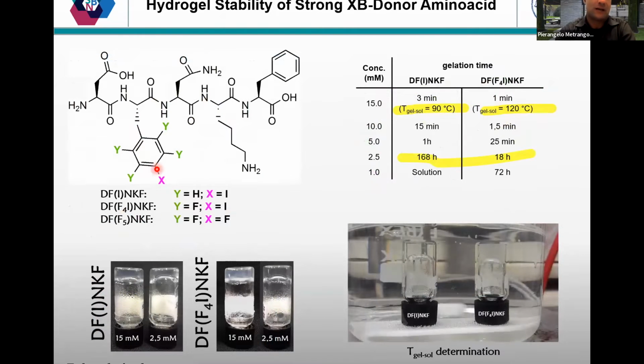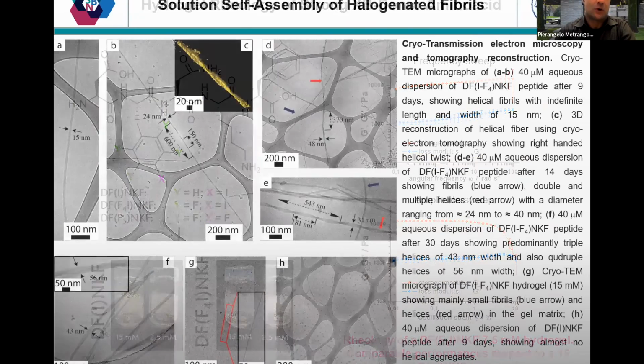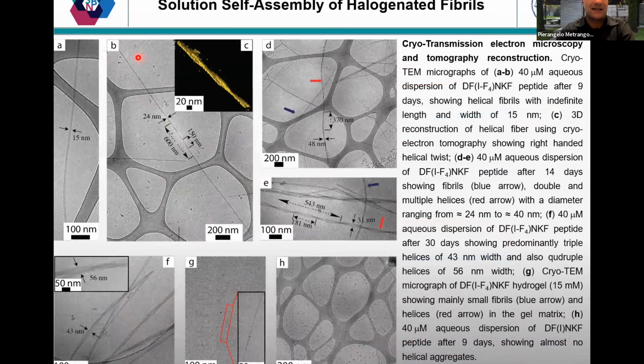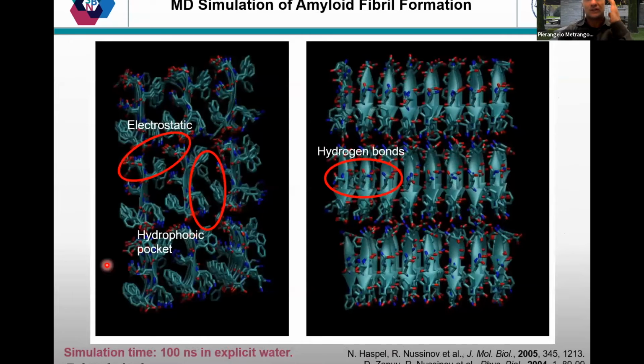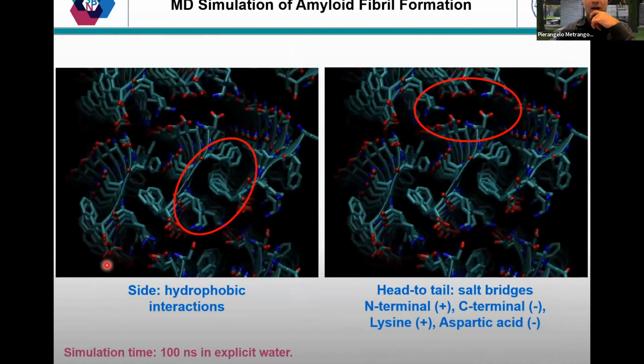So we took this fluorinated amino acid back to the full peptide, getting a much stronger gel compared to the former one, and much more complex helices, where you can see that this tetrafluoroiodo peptide makes very complex amyloid fibrils already at 50 micromolar concentration in water, and these helices are able to make even more complex structures like double helices, triple helices, and even more complex ones. So we wanted to understand a little bit more the binding, therefore we had to rely on computational methods. This is the hydrophobic pocket, which we are going to modify by halogen bonding.